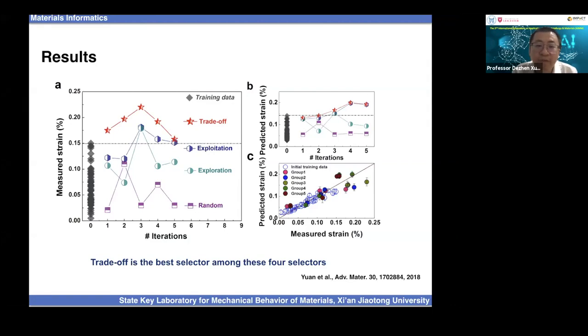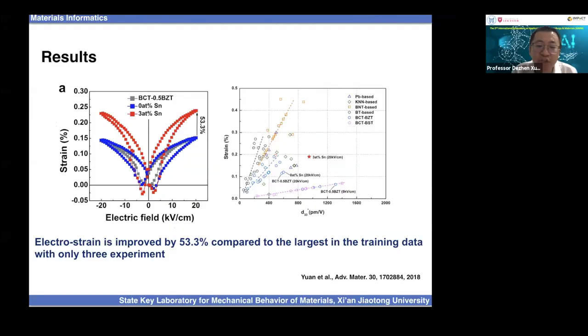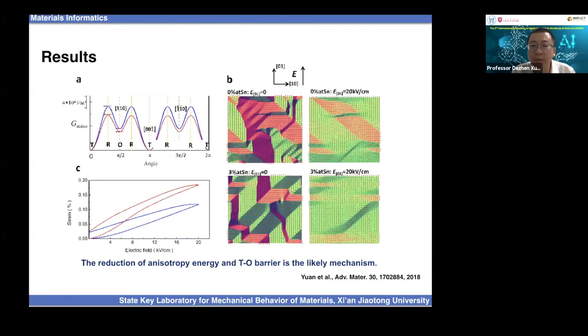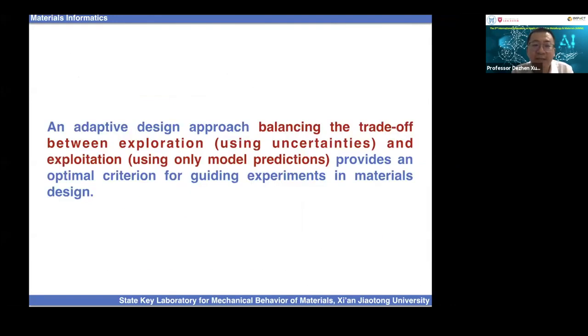So within only 3 iterations, we do 3 more experiments, we can improve the electrostrain by 53% compared to the largest one in the training set. So this is very efficient. So using such kind of selector to help the machine learning model, we can very quickly find the best material. And we explain our results by the DFT and phase field simulations. So we would like to say that the balance trade-off between exploration using uncertainty and the exploitation using the model predictions is a good optimal criterion for guiding the experiments in material design.